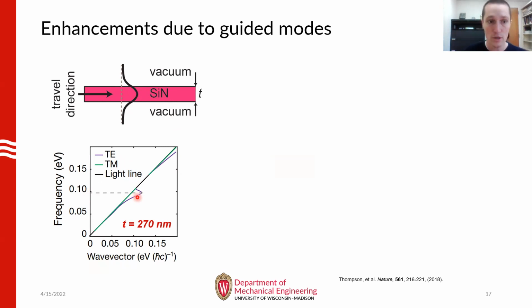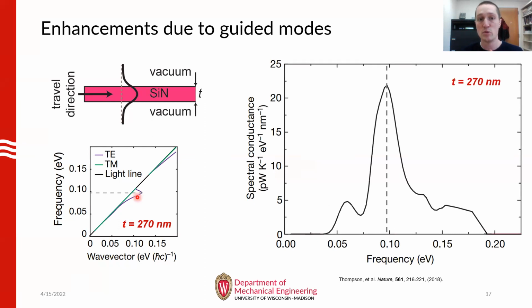What's interesting, though, is when you compare this dispersion relation to the computed spectral conductance between our 270 nanometer thick devices. As you can see, the spectral conductance is also peaked at that same frequency of 0.1 electron volts. So because of that spectral match between these two plots, that allowed us to conclude that it's these guided modes that are the specific modes responsible for these large enhancements in heat transfer.